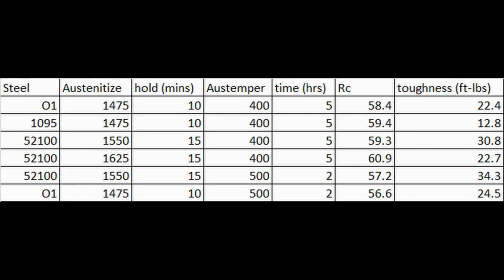Anyway, I tried an experiment where I austempered at 400 degrees, so it should be about half martensite, half bainite after I held for 5 hours, which is longer than necessary, but it should be fully transformed. The other experiment I tried, I used the same 400 degree Austemper, but I austenitized hotter. So I austenitized at 1625 Fahrenheit instead of 1550. Looking at some different journal articles, I estimated this to be the point where martensite start would be just under 400 degrees. Then we would have a comparison with the 1550 austenitized with 400 Austemper. So with the 1625, we would have all bainite, just formed at the lower 400 degree Austemper. So we can compare the properties of the two.